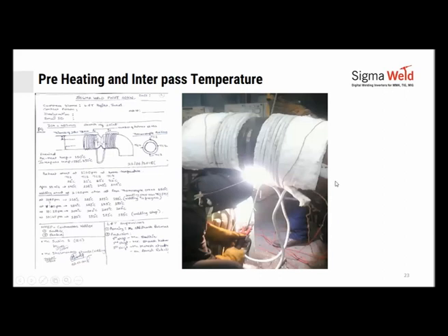This is another trial done for this equipment in use for pipe to elbow welding. During welding for this material, P91, the preheat temperature was about 150 degrees. It was achieved after 15 minutes. You can see that. And the job thickness is 72 millimeters. Achieved in 15 minutes, 150 degrees.